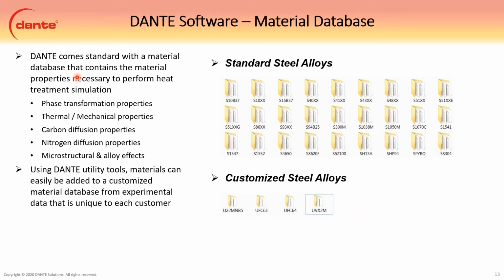But inside of that material data then is phase transformation properties, thermal and mechanical properties, carbon diffusion, nitrogen diffusion properties, and also microstructural and alloy effects are all included in these material properties. So this is a big deal because it's a lot of data for each material that has to be tested for. So to have this coming in is very helpful. And like I said, if you're close to one of these, and this isn't all of them, there's more, I couldn't fit them all here. If you're close, then generally we can make some small modifications to the hardenability if it leans one way or the other relative to these alloys, and at least get you close without doing any testing. And then you can do some minimum testing to kind of fill in the blanks. So starting from here, a lot less testing involved.